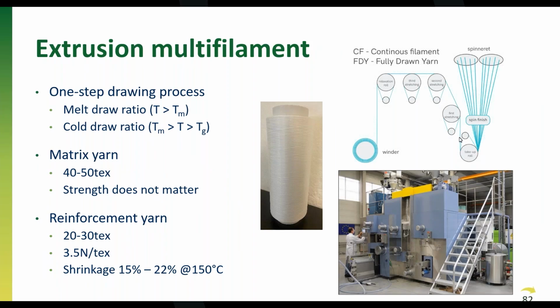And then in the second phase of the process, you have different heated rolls in which in between you can also again stretch the filament, and this is then what we call the cold draw ratio. And in this case, the temperature of the material is somewhere between the melting point and the glass transition temperature. For the matrix yarn, strength doesn't matter, as I said already, and we produce around 40-50 tex yarn with 60 filaments in the bundle. For the reinforcement yarn, the same. We work with those same 60 filaments in one yarn bundle.